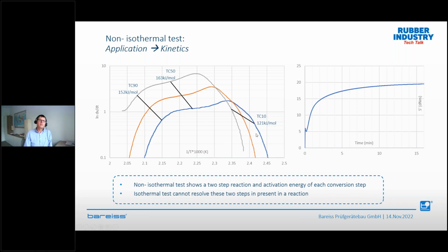And then you see here very nicely that you can calculate your activation energy depending on the conversion. And you see here nicely that you have a two-step reaction. So if you, for example, want to see on competition compounds what happened to the kinetics, you see much more than you see only on an isothermal curve.